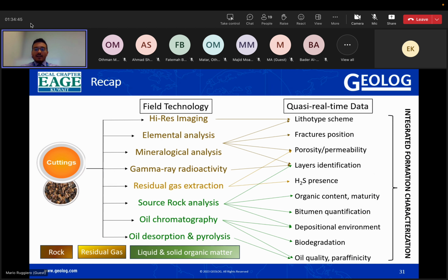So to recap, we have seen a very wide panorama ranging from organic to inorganic geochemistry, made possible by recent, very advanced technologies that have become robust and portable to be brought to the field. So you can apply these technologies in real time at site for high resolution imaging, elemental and mineral analysis, gamma ray measurement, residual gas assessment, so hydrocarbons and non-hydrocarbon, source rock analysis, oil chromatography, desorption, and pyrolysis, to assess quasi-real-time data and help in completion by having lithotyping, fractures, and porosity and permeability assessment, layers identification, H2S assessment, organic content and maturity assessment, identification of bitumens, biodegradation, oil quality, paraffinicity, for an integrated formation characterization.